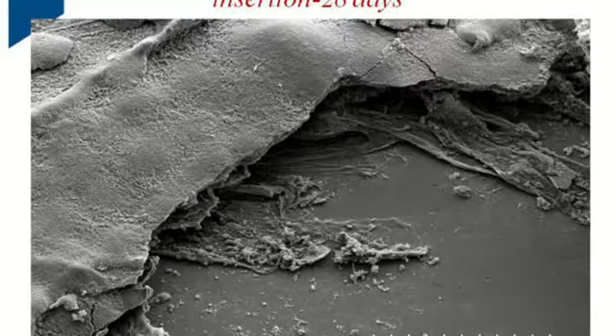If we look on this surface right here, we can see that it's now a ceramic material. So what the oyster has done is put down polymer, ceramic, polymer, ceramic, polymer, ceramic to cover this disc. Here's the growth front for the ceramic part. Then here's a layer of polymer again folded back, and then up here is more ceramic. So here's where it's uniformly coated on the other side of the disc, and then here's where the coating is fractured. So what we've been able to show is that A, you can take cells out of the oyster and grow a ceramic material on the metal surface, and B, you can do something very similar to how the oyster will grow a pearl: you can take a piece of metal, a foreign object, put it in the oyster, and then demonstrate how it grows up in multiple layers of polymer, ceramic.